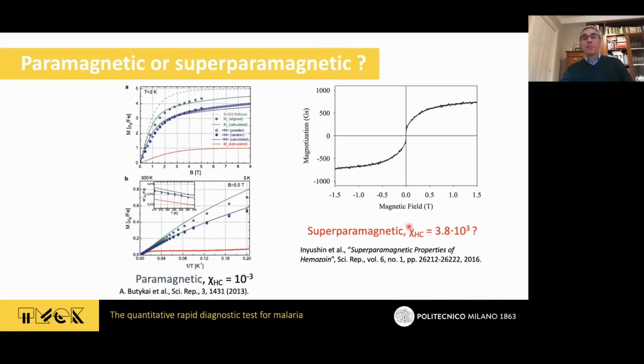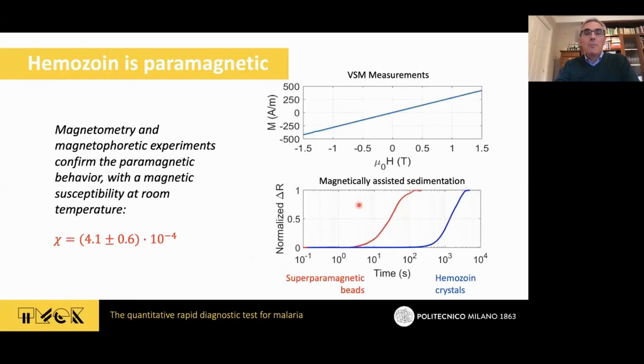What about magnetism? There was a strong debate at that time on the behavior, because in some papers you found paramagnetic behavior, in another paper superparamagnetic behavior. Okay, we made the measurements and we put the suspension in the VSM, we measure and you see this straight line which tells you that it's a paramagnetic behavior, no trace of superparamagnetism. And in this case we were using some synthetic nanocrystals made by Invivogen of the synthetic form of hemozoin crystal which is called beta-hematin, and the susceptibility was in agreement with literature, in the order of 4 × 10⁻⁴.